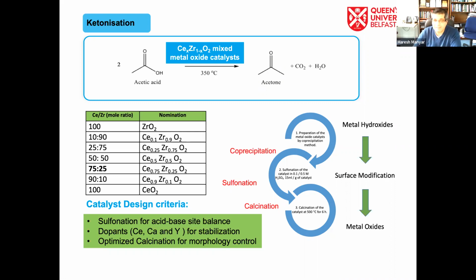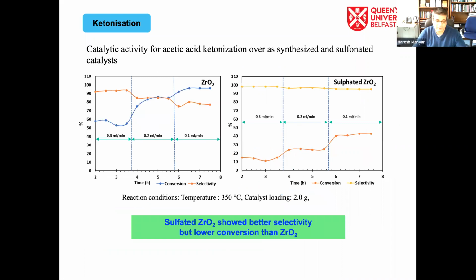And as we can see, we can modify these materials. The activity in ketonization is shown here. The pristine zirconia does show very high conversion, but over a range of very high conversion, the selectivity to the ketones drops down because of the byproduct formed from the condensation of the ketones. So this is the aldol condensation of ketones that occurs, which is a base-catalyzed reaction, which we don't want because that's a side reaction.